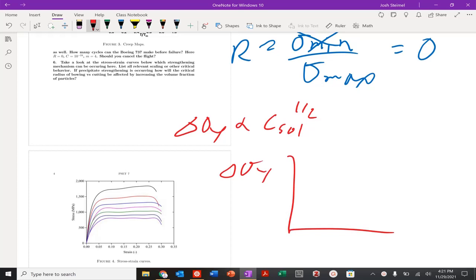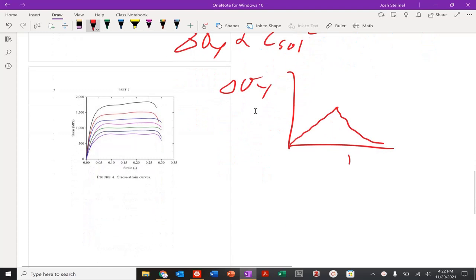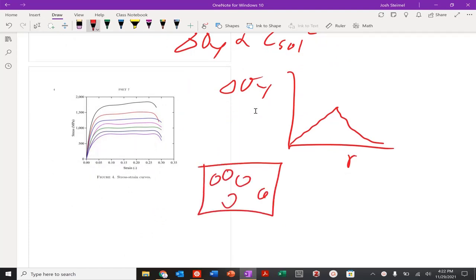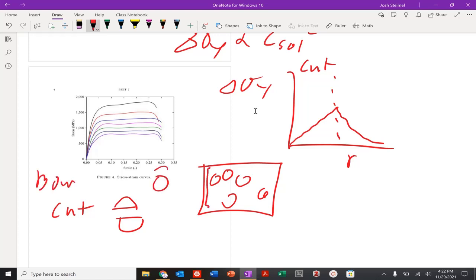or we could be looking at our yield strength equation for this, and then like that, for cutting and precipitate, basically precipitate strengthening. So adding precipitate particles, and we know that I have two contributions here. I could either cut or I could bow. If I cut, I am creating surface area, so that's my energy penalty. So I don't want to cut large particles because that's more surface area. I want to cut small particles.